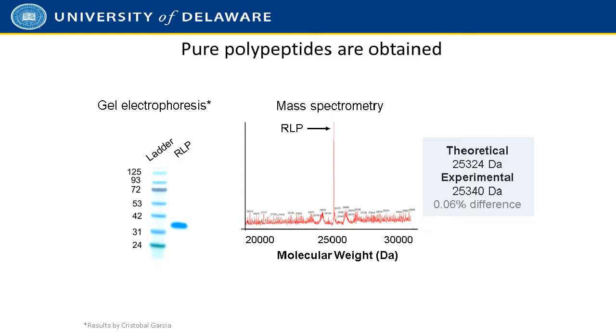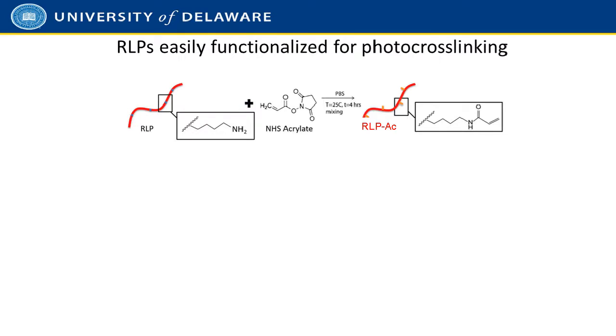And when we do MALDI mass spec of these materials, as you can see, we get a single mass to charge peak for the RLPs that is consistent with its theoretically expected mass. So mass spectra don't look any better than this. If you use a synthetic polymer, even the ones under the most highly controlled synthetic conditions, one will observe an envelope of different molecular weight species in their sample. So these materials are pure, they're a singular molecular weight, and we know by amino acid analysis that their composition is exactly what we expect.